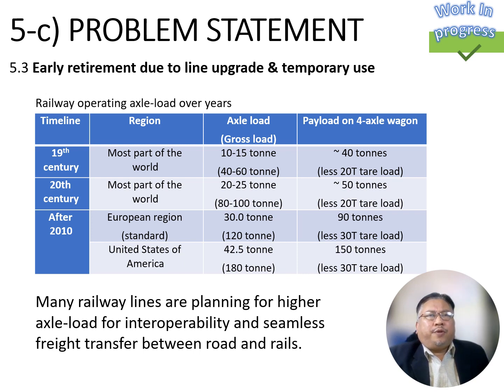There is also a problem with a number of rails being retired earlier than their intended design life. For example, in the earlier railways of the 19th and 20th centuries in most parts of the world, the axle load was about 10 to 20 tons per axle. Only after 2010 did most regions increase their loading capacity, to a maximum now in the United States of about 42.5 tons per axle. Therefore, those railways still in service but unable to cater for higher carrying capacity will be removed from the line and become part of the wastage if not treated as serviceable rail.